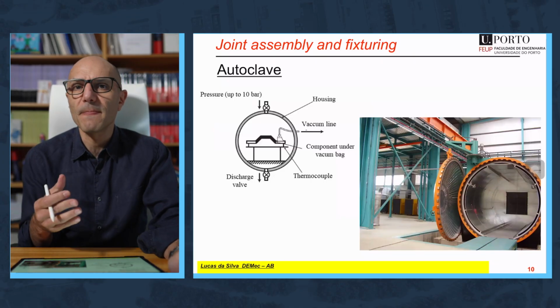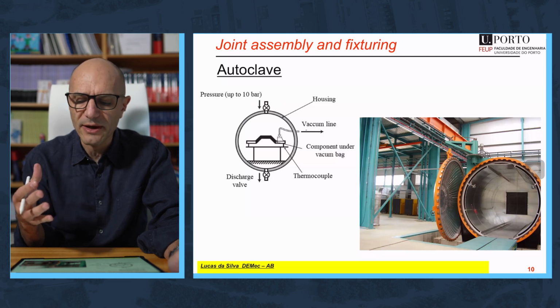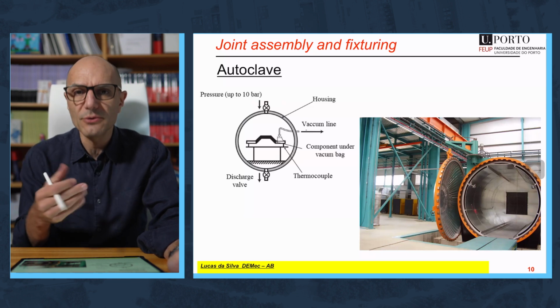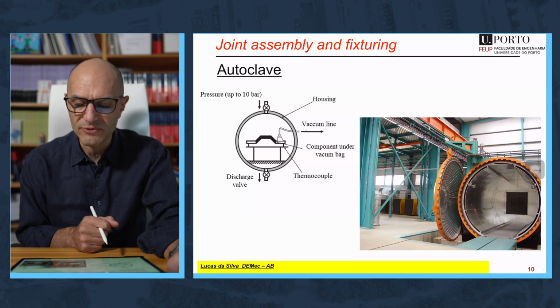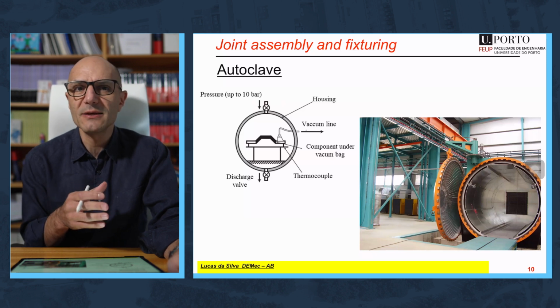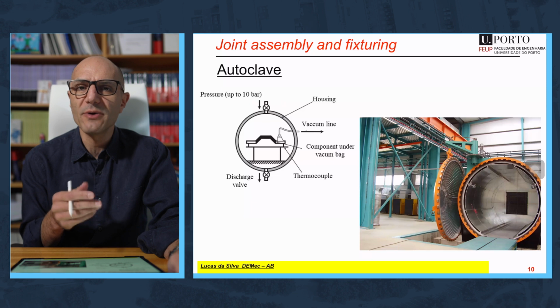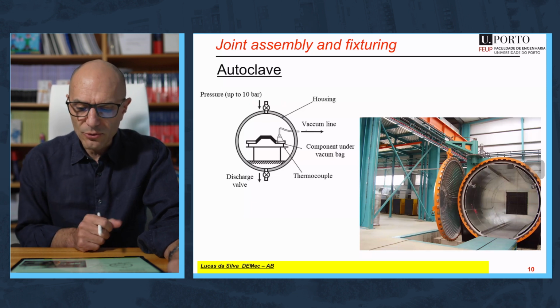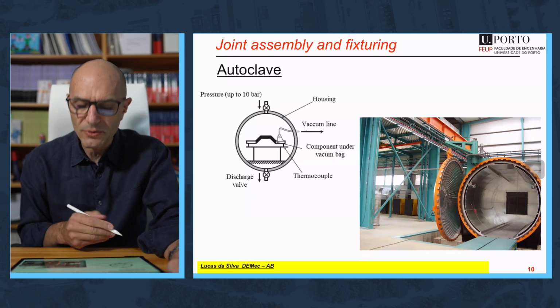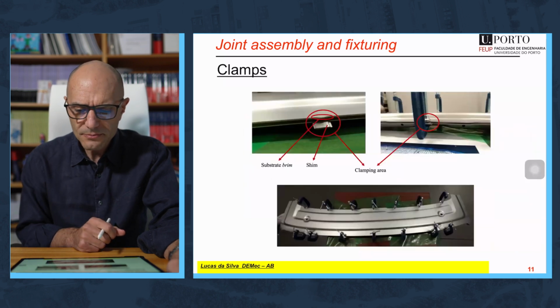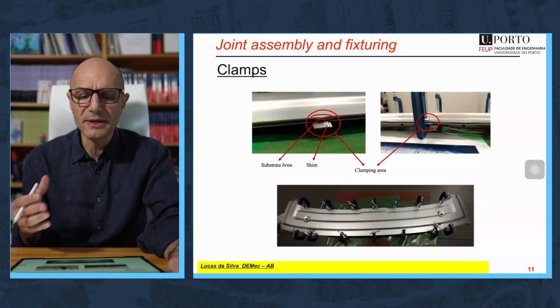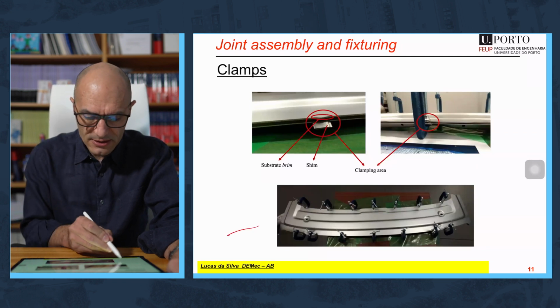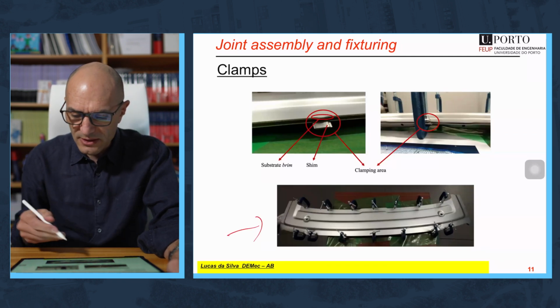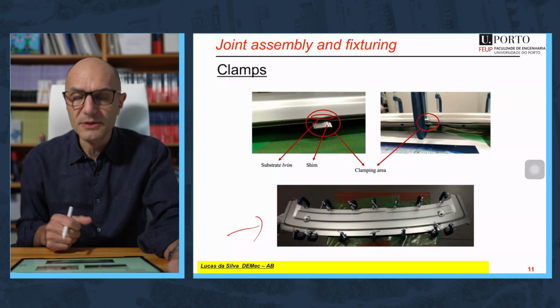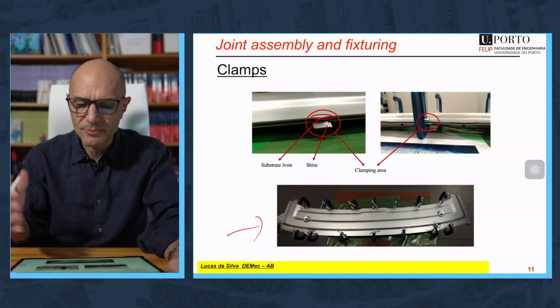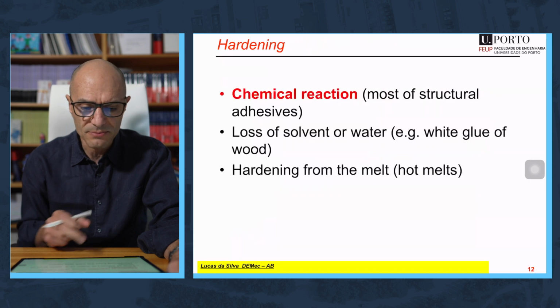A device that is very common for composite materials is the autoclave, and you can also use it in the context of adhesive joints. This is especially indicated for joints where you have an adhesive film. It controls very well the pressure, which is also important to avoid air entrapment. In industrial situations, many times clamps are used, such as indicated here. This is in the automotive industry for a particular component, but in aeronautical and aerospace, it's also common to use clamps.